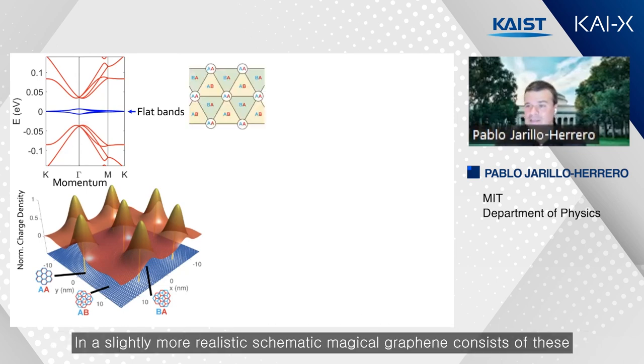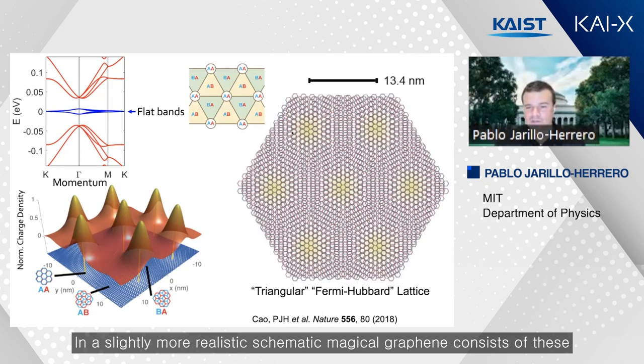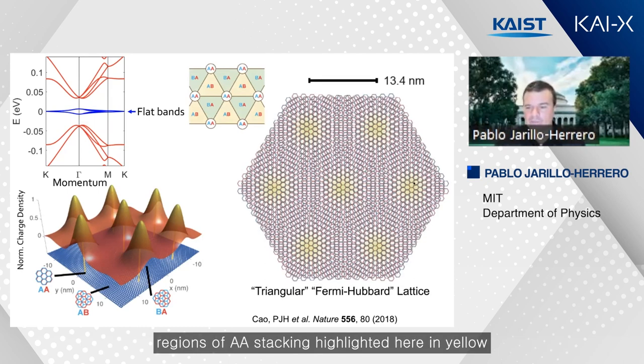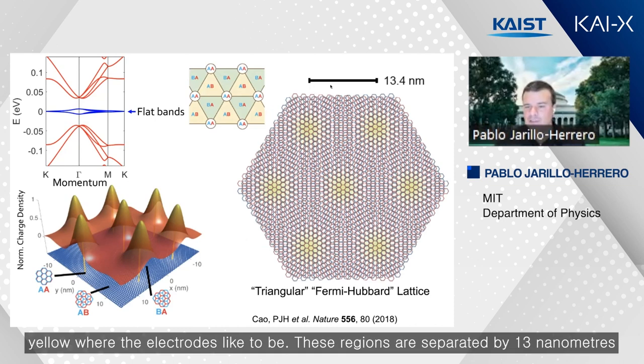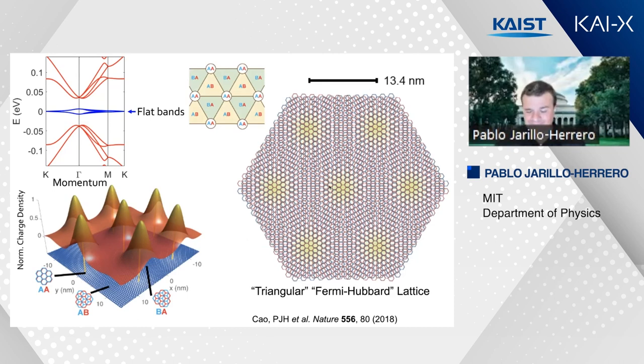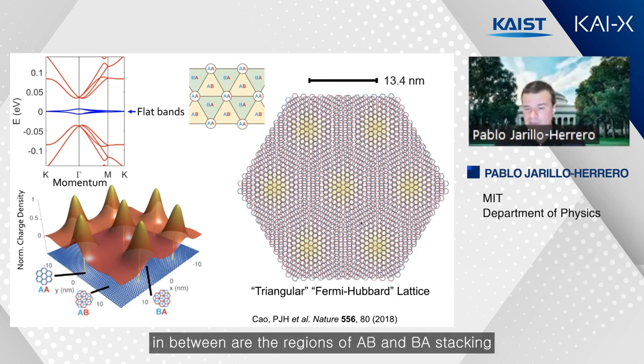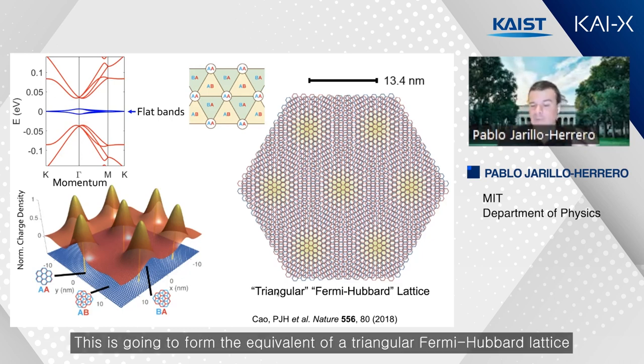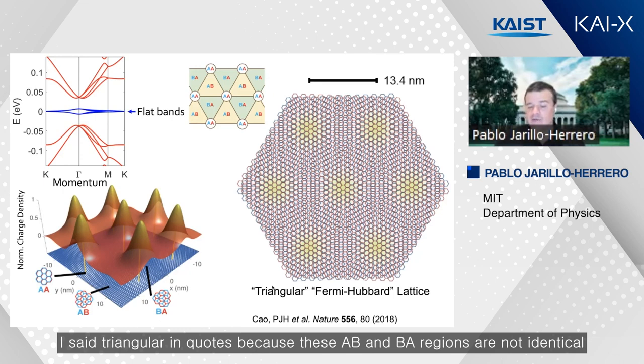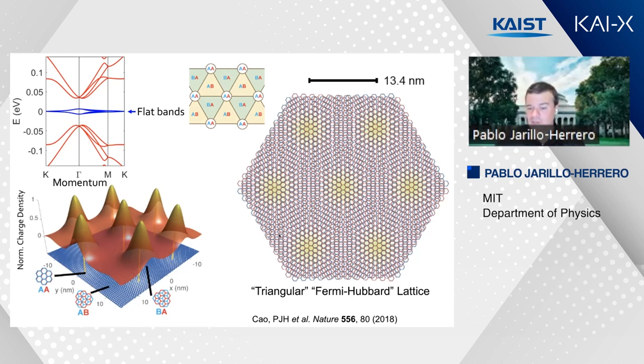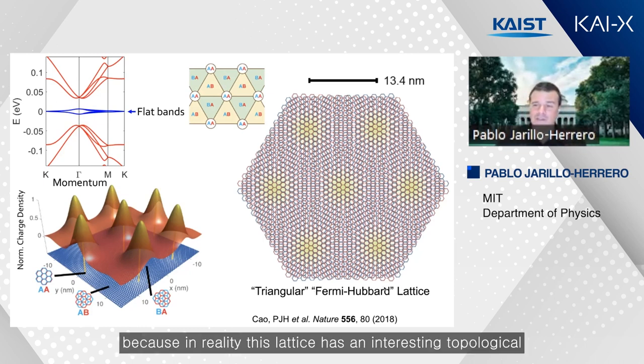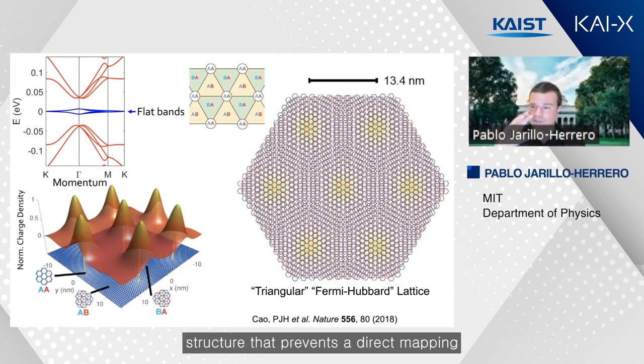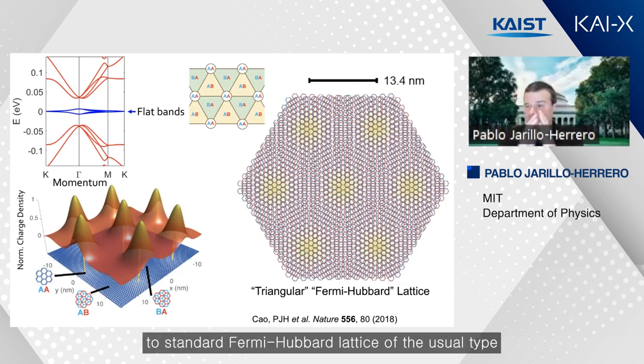In a slightly more realistic schematic, magic angle graphene consists of these regions of AA stacking, highlighted here in yellow, where the electrons like to be. These regions are separated by 13 nanometers. And the regions in between are these regions of AB and BA stacking, okay? This is going to form the equivalent of a triangular Fermi-Hubbard lattice. I said triangular in quotes because these AB and BA regions are not identical. So in reality, this is a honeycomb structure. And I put Fermi-Hubbard in quotes because in reality, this lattice has an interesting topological structure that prevents a direct mapping to a standard Fermi-Hubbard lattice of the usual type, okay? But you get the idea that this is something which is going to be a little bit like those cold atom lattices.